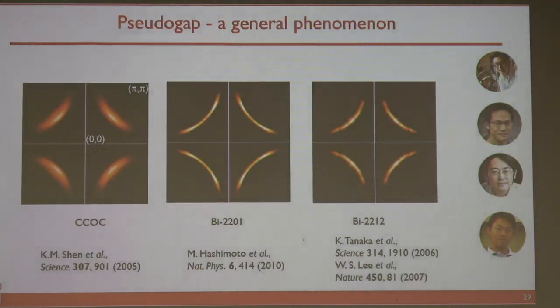In most of the cuprate superconductors, the so-called carriers are hole-like, positive. So in this case, the pseudogap happens near the Brillouin zone boundary. Okay. Under these circumstances, it is difficult to know what the microscopics is because too many things happen at the zone boundary. There are Van Hove singularities, there's collective mode coupling, and these boundaries also happen to be where the Fermi surface crosses the underlying antiferromagnetic zone boundary.